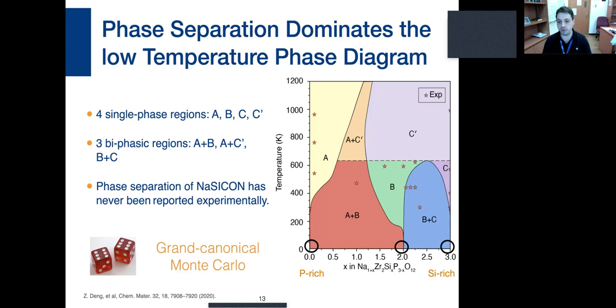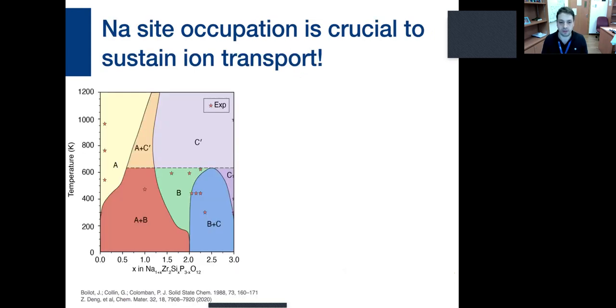Theory tells us the system should phase-separate in the rhombohedral phase. Experimentally, we don't find phase separation. We can learn more from the phase diagram. This is the data, the red stars, for Boilot's French group using neutron diffraction and single crystal samples of NASICON. If I place myself at around 450 Kelvin and try to extract the occupation of the various sodium sites, sodium-1 and sodium-2, in the computed phase diagram, this agrees very well with the stars. Blue stars show the occupation of sodium-1 from experiment, red stars the occupation of sodium-2 from experiment. At zero sodium content, sodium-1 is fully occupied. At x equals 3, four sodium in the structure, sodium-2 is fully occupied.